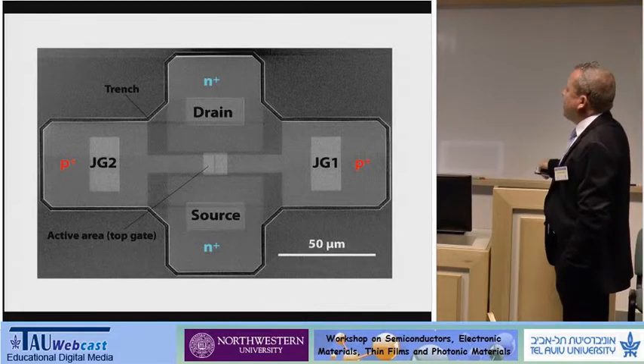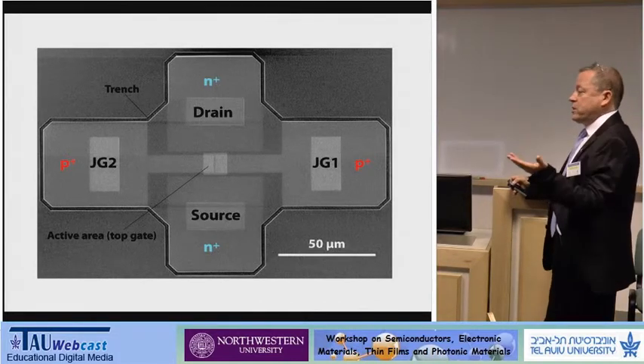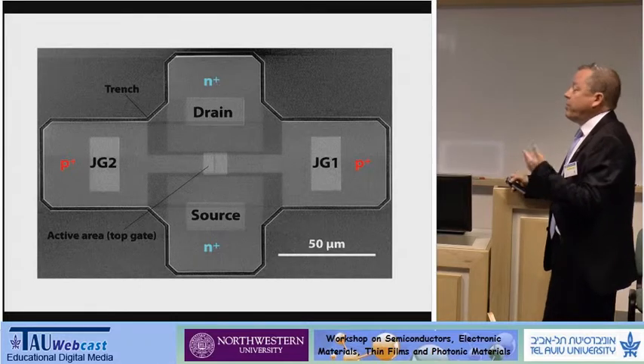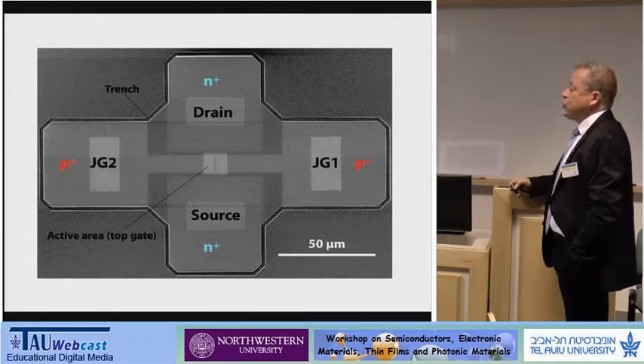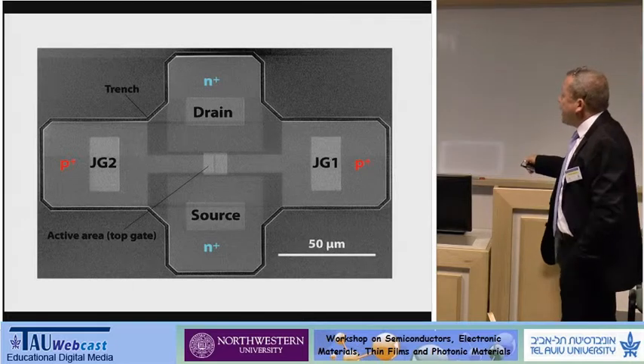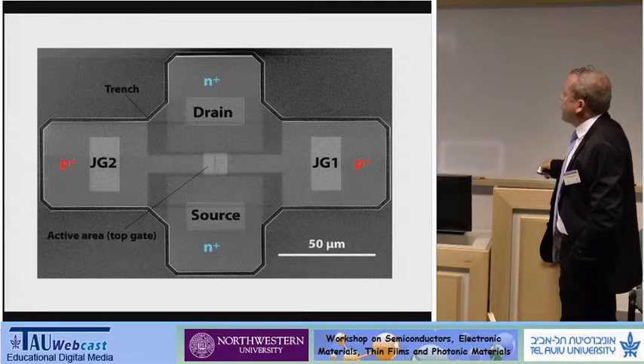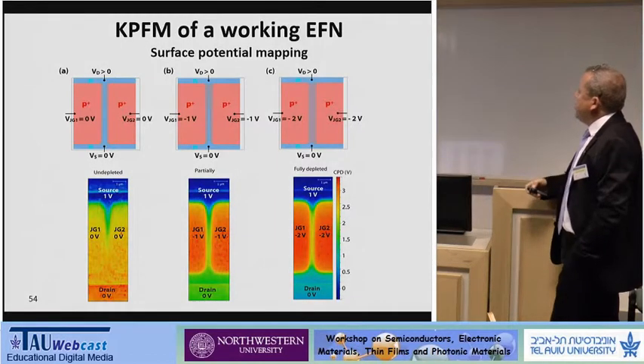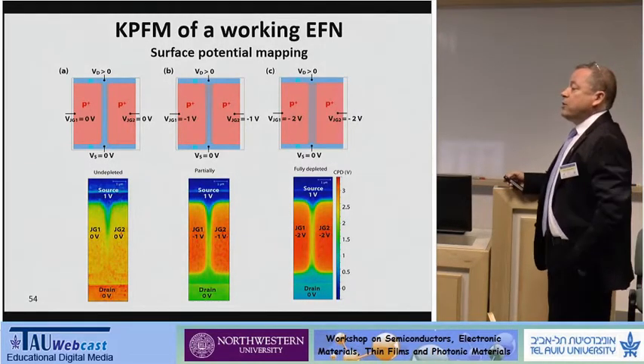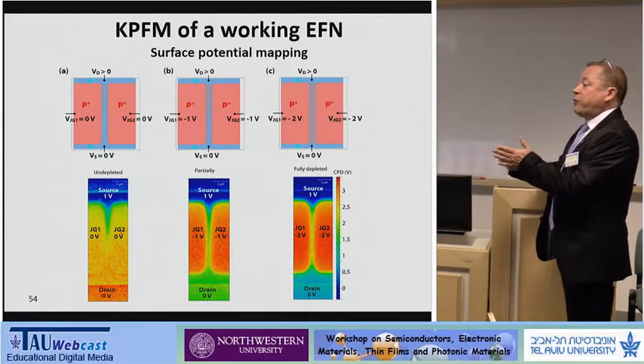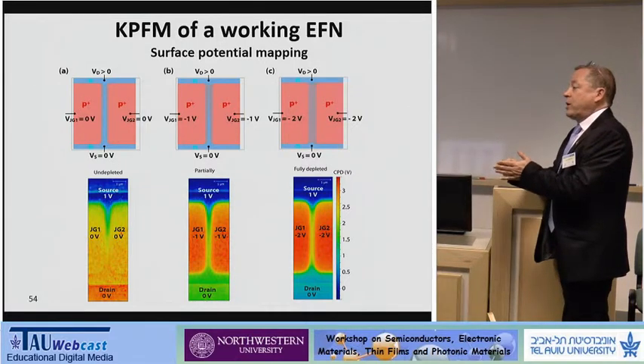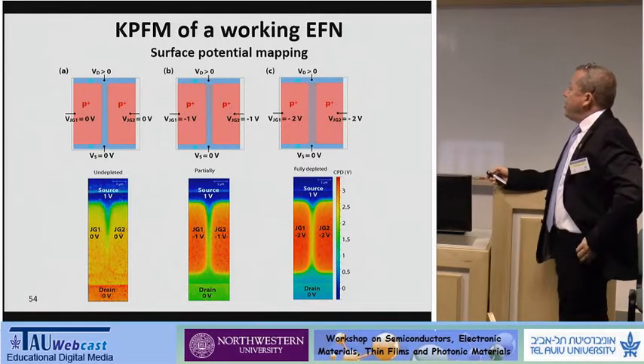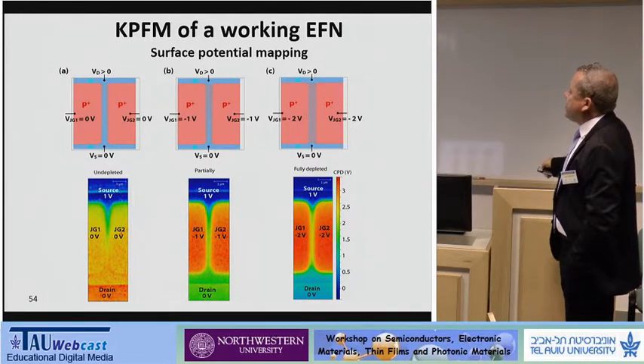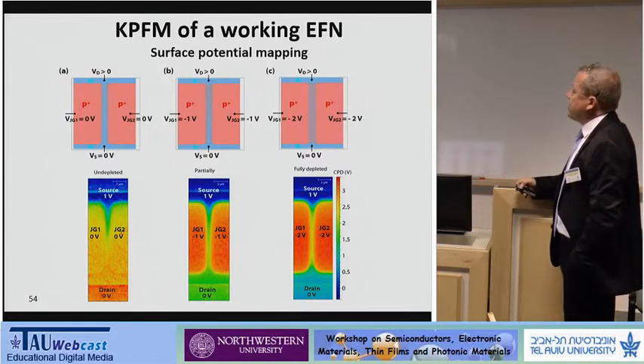So this is fairly large. You can see the scale here simply because we want to test it in the lab and work with big pads. These are the pads of the side gates, to work with probes. And the channel is only here. And these are the two side gates, the contacts to the two side gates. And what we can do very nicely is to measure this confinement of carriers, or this reduced dimension of the nanowires, by KPFM. What you see here is a cartoon, and these are real KPFM measurements of the potential profile from source to drain.